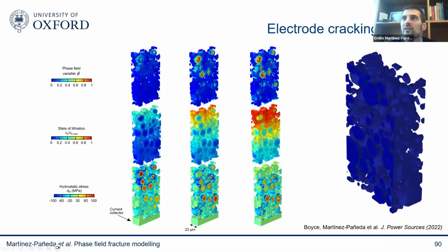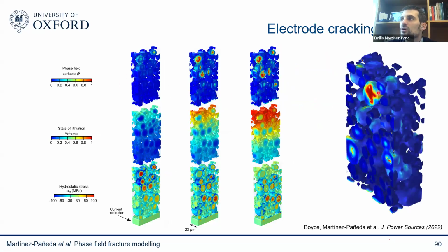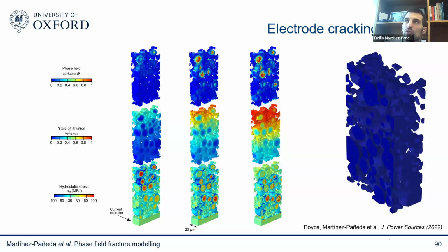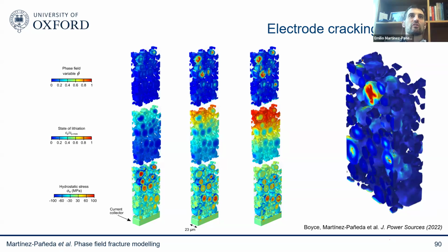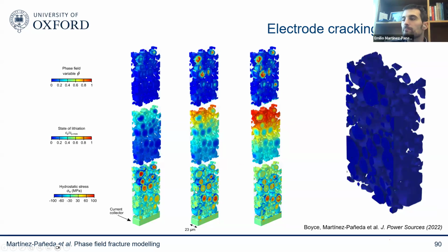And we can do that in 2D and 3D. And you can see how those cracks start to evolve. We can learn things about the heterogeneous electrochemical nature of this process. We can understand, for example, what happens if you reduce the thickness of your electrode, and we can see which batteries are more affected. You see here the content of lithium, the phase variable, and the hydrostatic stresses.